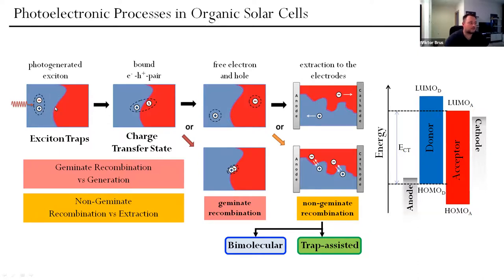That's why the domain size of donor and acceptor networks should not be larger than 20 nanometers, plus or minus. However, if we have too good solubility of donor and acceptor and we make these domains much smaller, it will be efficient for excitons to be split. But in that case, it will be a challenge to extract charge carriers, because they need to move,